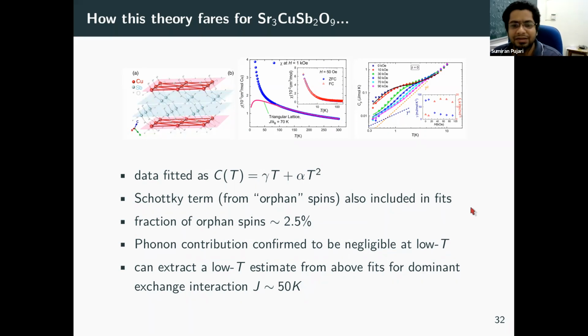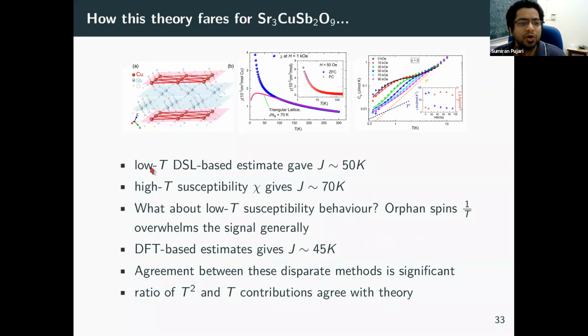Some additional details: orphan spins and a Schottky term. These non-interacting spins always have to be included in real data, but their contribution is small enough. We can also confirm that the phonon T cubed contribution can be neglected in this temperature regime. And given all this, I can extract a low temperature based estimate for the exchange interaction J. If I do the fitting properly, I extract that this dominant exchange interaction scale should be around 50 Kelvin. So this low temperature DSL-based estimate gave us 50 Kelvin.